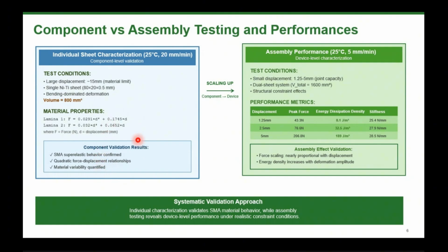Then once we characterized the sheets, we scaled up and moved to characterizing the assembly performance at ambient temperature and at 5 millimeters per minute rate. And what we found are the values reported in this table, which say that force scales near proportionally with the displacement, while the energy density increases more than proportionally with the deformation amplitude.